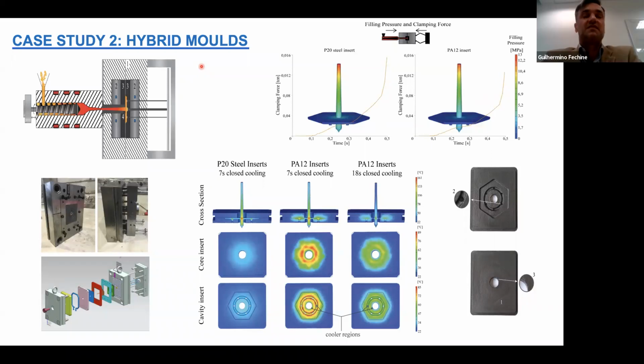Because if you think about percolation, for thermal conductivity and electrical conductivity it is quite different. Yes, for thermal you have a low amount of filler because you don't need to have this contact between the fillers. Yeah, indeed. For the resistivity for sensors, you do not want to have the contact, but you want to control the dispersion, the position, to have a good sensitivity of your gauge factor and so on.